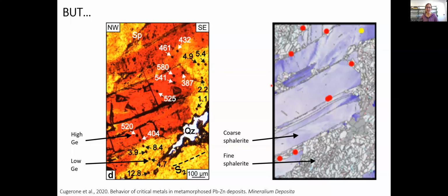So several studies have found that the modification of sulfides during deformation and metamorphism can significantly change that original critical metal distribution. So for example, these images are from a study by Cugerone et al. 2020, and they show germanium-bearing sphalerite. On the left, we have a transmitted light photomicrograph. The dark areas are germanium-rich. The pale areas are germanium poor, the yellow ones. And the labels show germanium content in ppm.